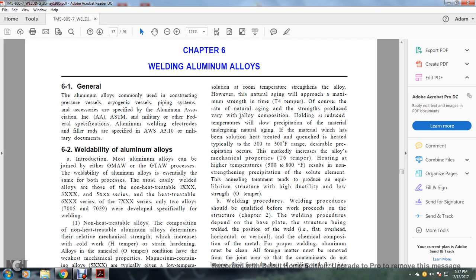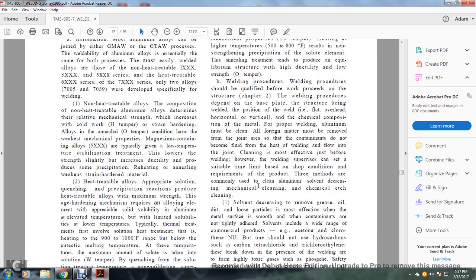If the material which has been solution heat treated and quenched is heated, typically to the 300 to 500 degree range, the desired precipitation occurs with a marked increase in the alloy's mechanical strength, the T6 temper. Heating to a higher temperature of 500 to 800 degrees Fahrenheit results in non-strengthening precipitation of the solute elements. The annealing heat treatment tends to produce the equilibrium structure with high ductility and low strength, the O temper.